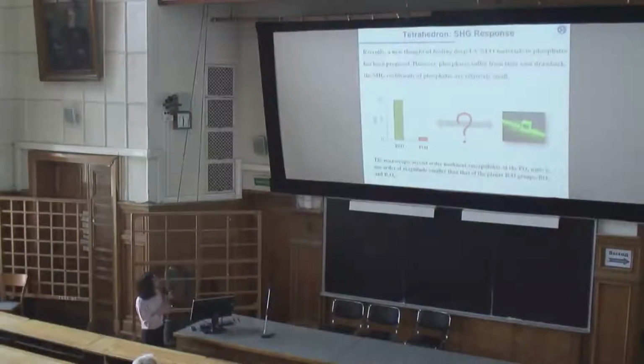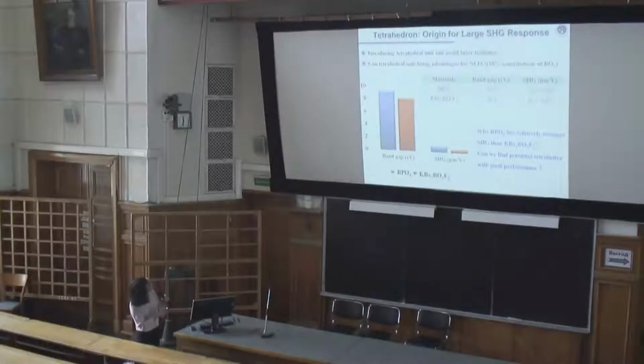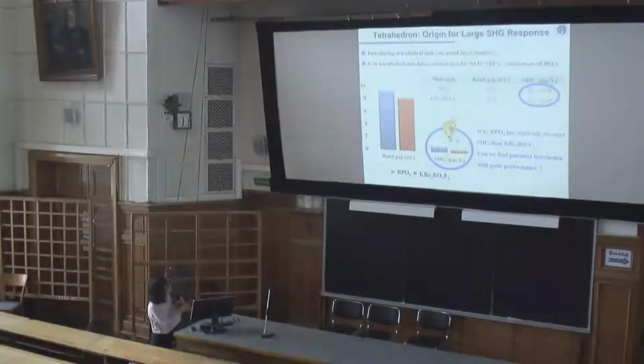So let's go back to the tetrahedral group. Recently, there are some phosphates. We can see that for the tetrahedral group, usually the SHG response is smaller than that of BO3, but still there is another reason for this. Here we can see these two compounds, this is boron phosphate. It has a large band gap and a large SHG response, but usually it cannot give a balance for this. What's the reason? Because usually a large band gap should have a small SHG response, but here they still have a large band gap and a large SHG response. So what's the reason for this?